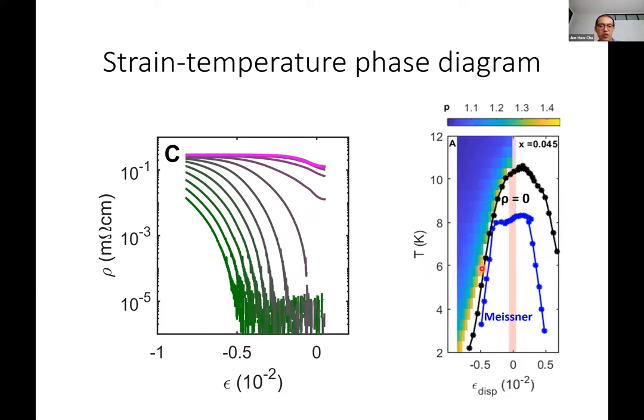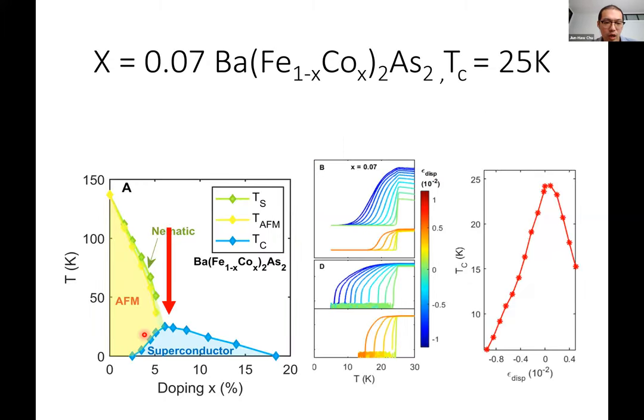This is the underdoped case. Now, this can all be interpreted in terms of competing order, where you're just increasing the antiferromagnetic order and, as Pengcheng mentioned, increasing T-Neel and gapping out more carrier density. So what about the optimal doping? For optimal doping, we choose this composition, 7%, where there's no long range magnetic and structural order. But still, we're seeing a very large suppression of superconductivity with strain. This is the resistance versus temperature curve. Again, with both tensile and compressive strain, the Tc goes down very quickly from 25 Kelvin all the way to 5 Kelvin within about 1% of strain.